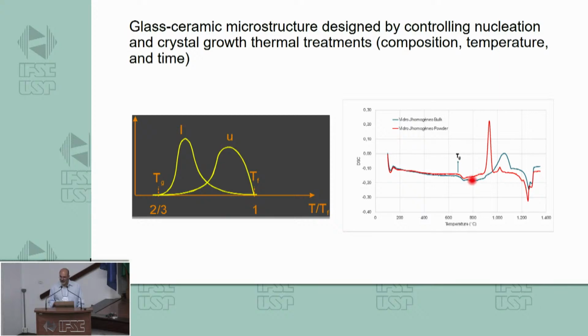If we have a very good glass former, after Tg, we don't see crystallization and we don't see melting. It's only a flat, horizontal line. This result can change very much depending on your sample. If the particles are coarse, the size of the particles is large, you have a broad peak. If you mill it, grind it into a finer powder, you have more surface to crystallize, and in general, surface crystallization predominates, deviating the peak to lower temperatures.